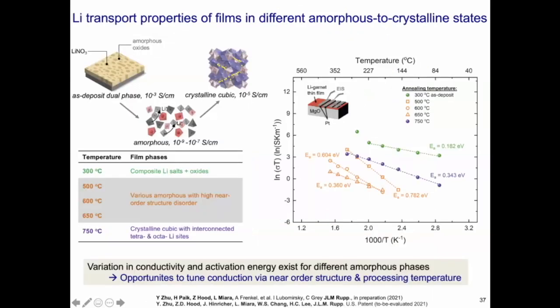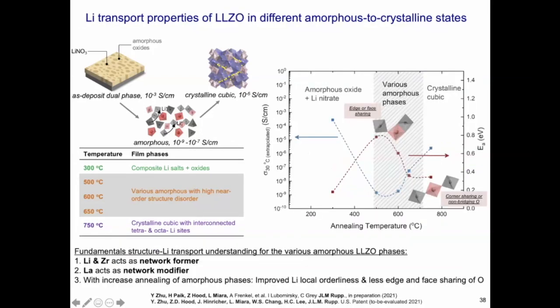Now, what I want to show you here is that the impact on conductivity is striking. You can see in orange different amorphous, tailored phases that exist for the lithium garnet in the Arrhenius diagram. And depending on what temperature you use to freeze the amorphous structure in the manufacture, you can see very different overall conductivity compared to the cubic one. This is very exciting because that correlates back to the huge structure changes that we observe here. So when we look, for instance, at the conductivity over the post-annealing temperature, we can see that for the various amorphous states, depending on how the building blocks are connecting, we have different conductivities, which have a maximum around 450.